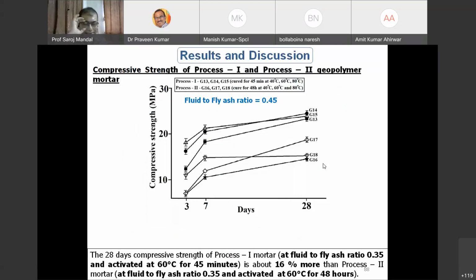Naturally, in this case, what I have seen is that when we mix only the fly ash and the activator fluid, the mixing becomes very uniform, and you get a very good amount of paste. Whenever you put some sand after that, the paste becomes uniformly distributed inside your sand. But in the earlier case, process 2, where sand and fly ash are mixed and then we add some activator, there is some mismatch between the activator and the fly ash. So that's why process 1 is better than process 2.